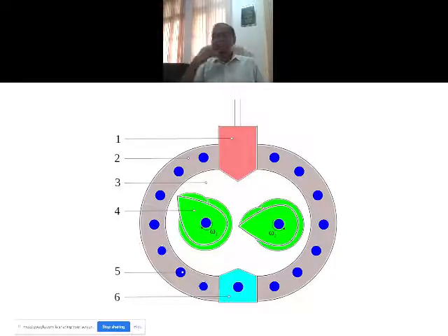So you see the advantage in terms of output. But keep in mind, the extent of dispersion that you get in the output for this internal mixer, what I say is the quality of the mix or the dispersion level, is obviously inferior to what is happening in a two-roll mill. So here you get higher output, huge bulk volume, but then the dispersion is not as desirable. So what you do is, that is what you have seen before. The thing will be dropped onto a series of rolls, as you have seen a little bit earlier, and then it will be refined in every consecutive roll, and finally the sheet will be stored.